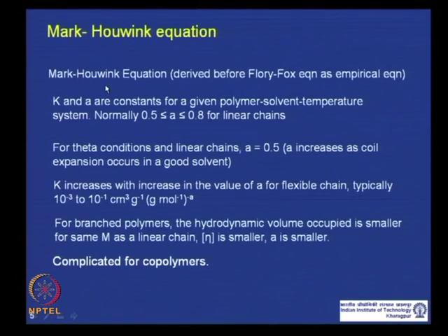As I said, the Mark-Houwink equation was derived before the Flory-Fox equation as an empirical equation. Now, K and a are constants, and they are constant for a given polymer, solvent and temperature system. So, if you change any of these three, polymer, solvent or temperature, then the K and a values will change.